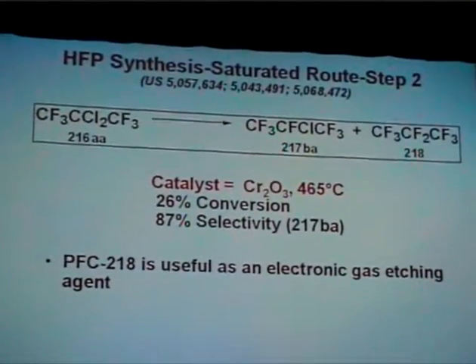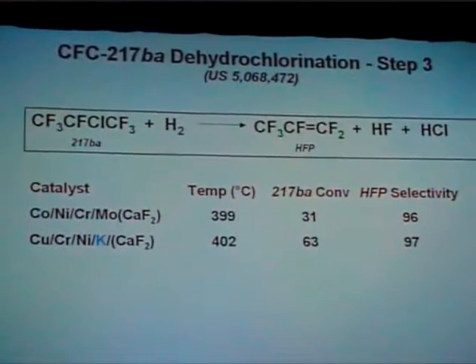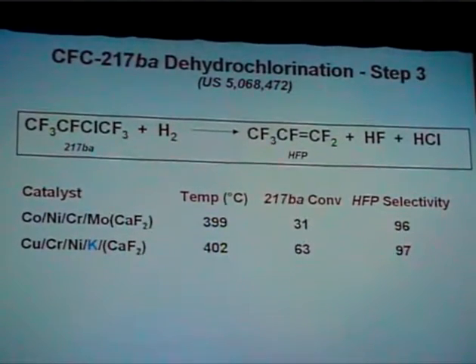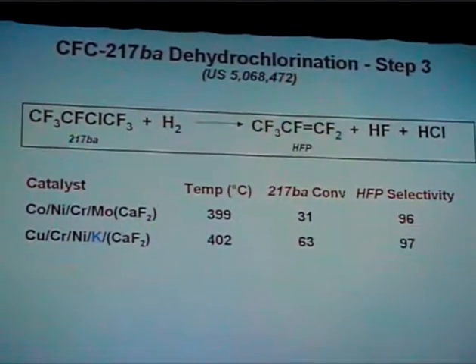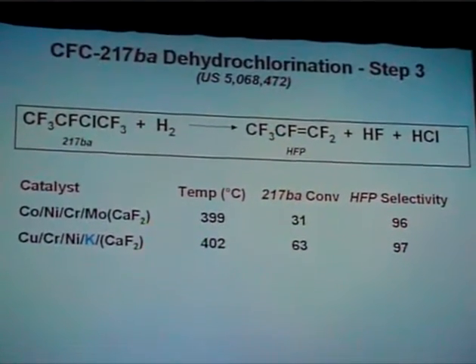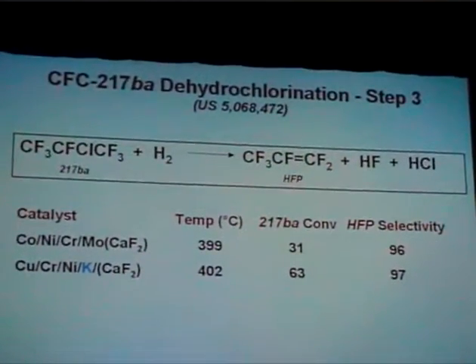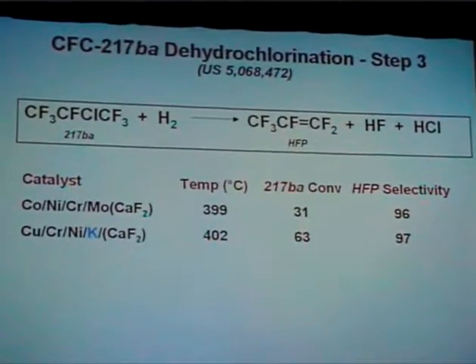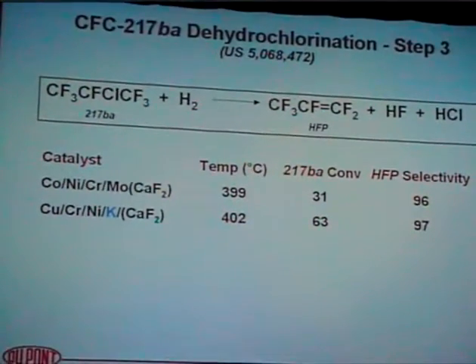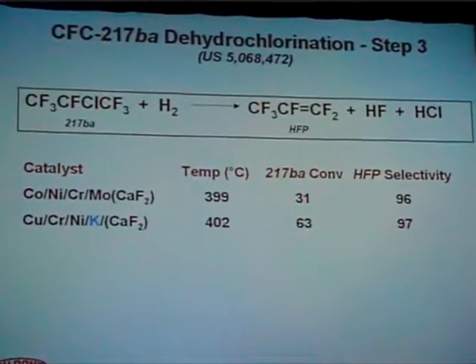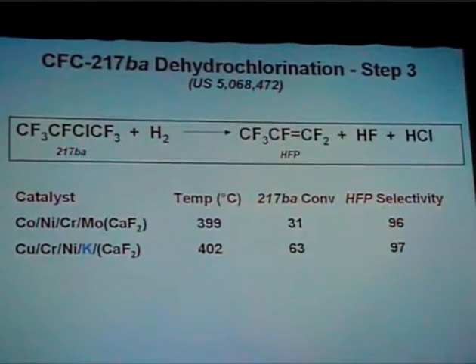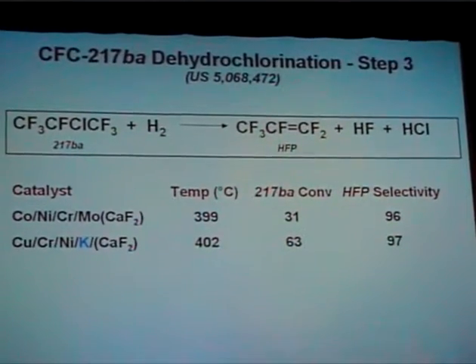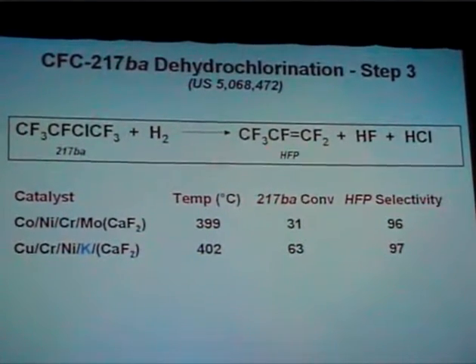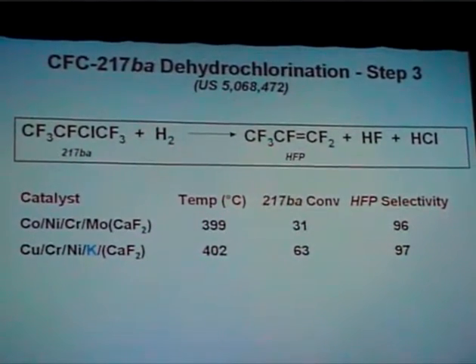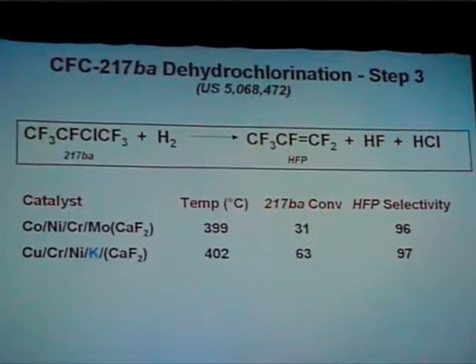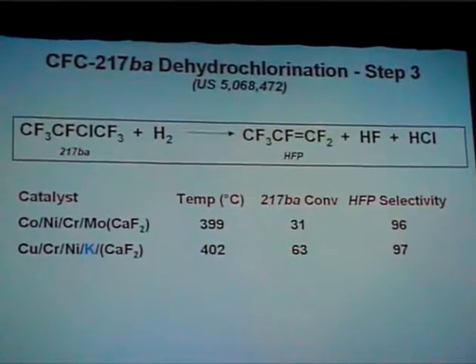The next reaction is to make the olefin. And this is some very fine work done by Bill Minot. And just look at that reaction. You're taking a very stable chlorofluorocarbon, reacting it with hydrogen, ripping out HF and HCl to give hexafluoropropylene. And Bill found that of a variety of catalyst materials, calcium fluoride by far was the best support for this dehydrochlorination reaction. Promoting it with potassium is also a very important finding. Look at the selectivity, 97% selectivity to hexafluoropropylene at 400 degrees or so centigrade. So very nice piece of work, very low catalyst deactivation in that process. So that's the saturated route to hexafluoropropylene.